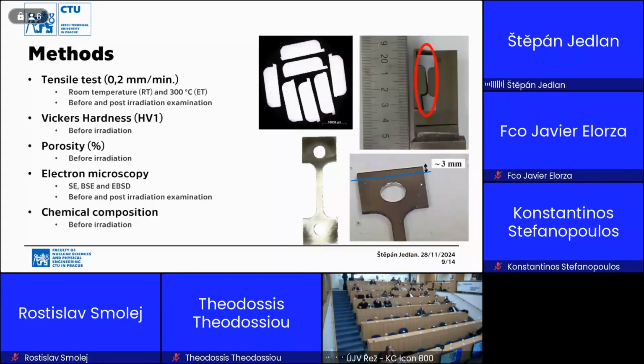And now for the tests that we did: the tensile test, hardness, porosity, then light optical microscopy and also electron microscopy and chemical composition. However, only the tensile test and the electron microscopy were done on irradiated material. Nowadays, the nano indentation is going through. We weren't able to do it yet, but now it's going to. The measurement is being done, and the tensile tests we did at room temperature and 300 degrees Celsius, because we wanted to compare them to the literature and to the standards.